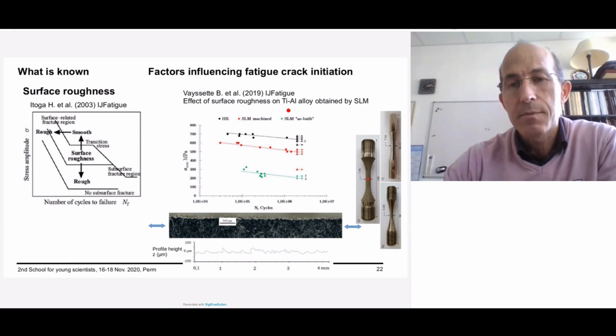In red, this is as built by SLM surface with a bad quality. You can see here the roughness, which is very bad. The scale here is 500 micrometers. So if you do not machine the roughness, the surface, to improve its quality, you have a very sharp decrease of the fatigue resistance, approximately a factor of 2. So this proves that the roughness is very important in the fatigue resistance because the valley of the roughness profile plays the role of a micro notch.